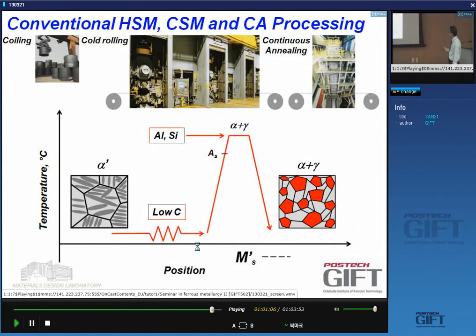So the cold rolling, again, if you use the martensite route, you will need to reverse martensite route, you'll need to have a very low carbon martensite. Otherwise, you'll have mechanical difficulties. The intercritical annealing is not a problem, certainly not with these aluminum additions. I've shown to you that the best conditions for the annealing are very close to what is industrially used, and then the cooling is not very critical in terms of cooling rates.